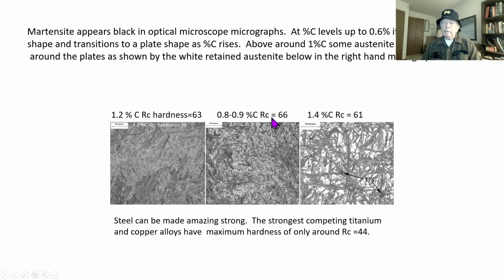Now, up here I have listed the Rockwell hardness of the various martensites. And notice how hard they are. The hardest is the lower carbon, 0.8 to 0.9. At 0.4, it's still around 60. And at 1.2, it's dropped to 63, and at 1.4, it's dropped to 61 due to all this retained austenite.